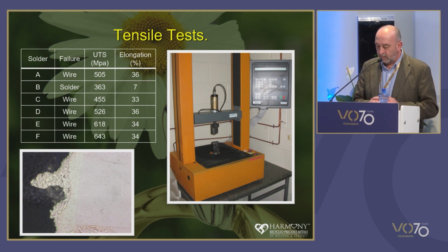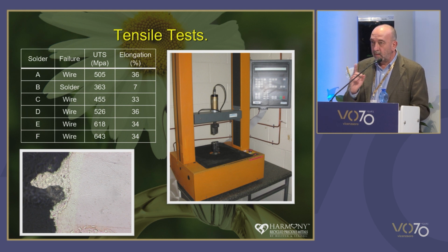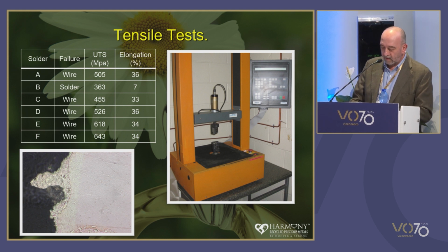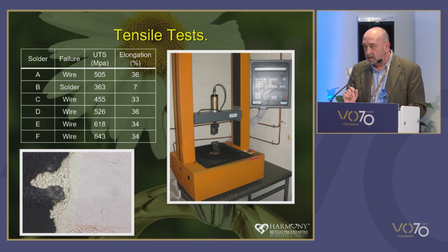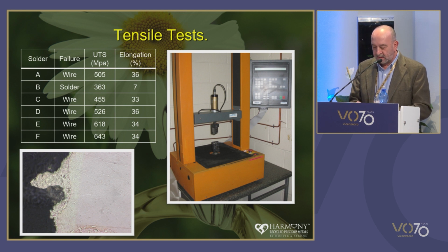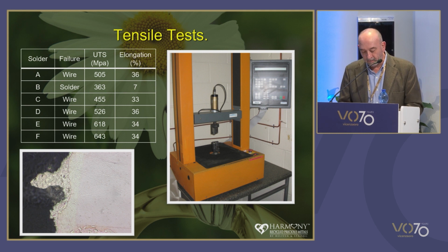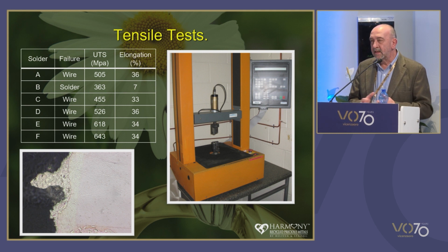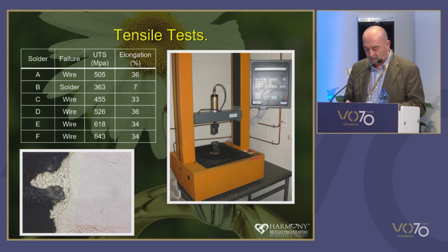The first sample we prepared with the joint faces butted close together and flush, and we used 1 piece of solder. The next, we actually used feeler gauges to gap it, and we gapped 1/4 millimeter, and then we used 2 pieces of solder. And the third test, we gapped it at 0.5 millimeter, and we used 4 pieces of solder. And for each solder to be tested using the hand torch, the jeweller was instructed to heat the sample until the pieces had melted, and then to remove the heat source straight away.